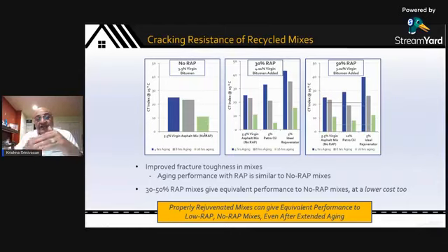Predictably, as you can imagine, the properties of the mix fall as you age it more and more. The fracture toughness falls more and more as you age it. We took this chart and just put it out here and compared it to 2 mixes, one with 30% RAP and one with 50% RAP. In case 1, we added 5%.